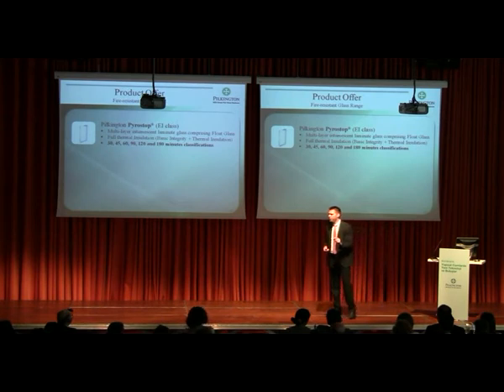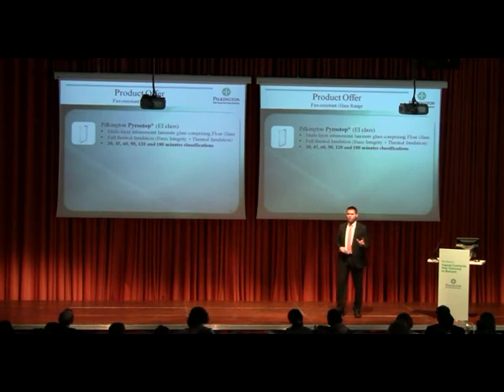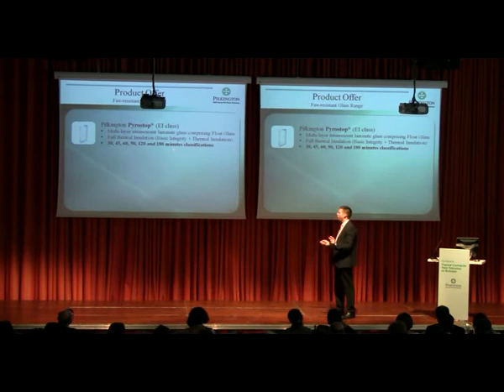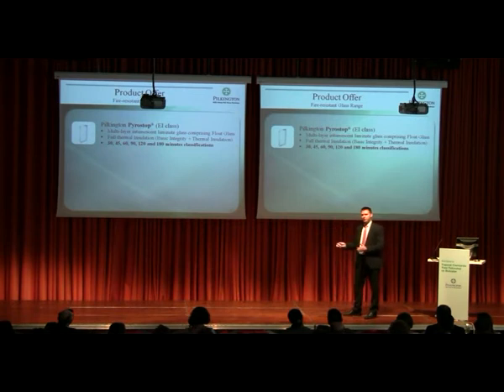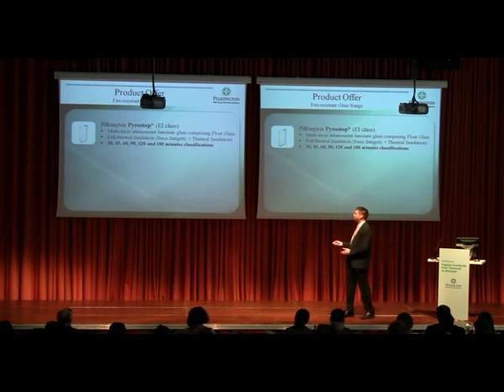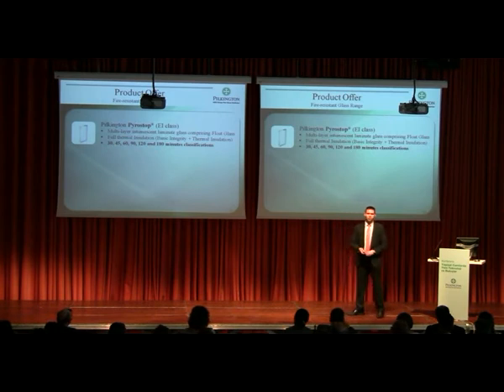Its weight is about 30-35 kilo per square meter, and the type for 3 hours is 94 millimeter thick, with a weight of almost 200 kilogram per square meter. So you see, the higher the requirement is, the thicker the glass will be, the more interlayers are inside, the more interlayers we need to react, but it's possible to achieve even 3 hours fire protection with such a huge and big and thick glass.